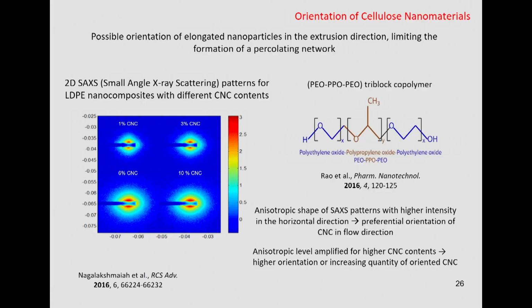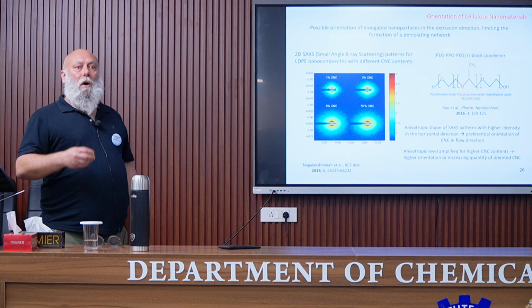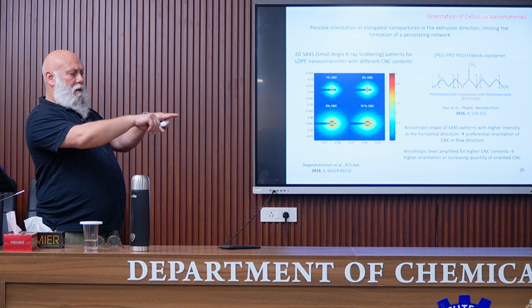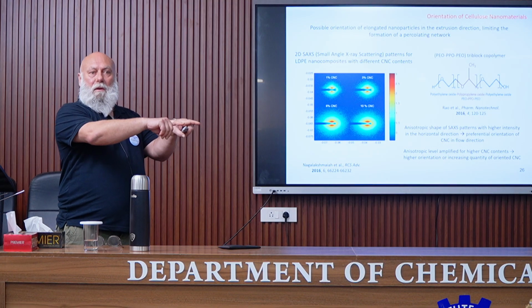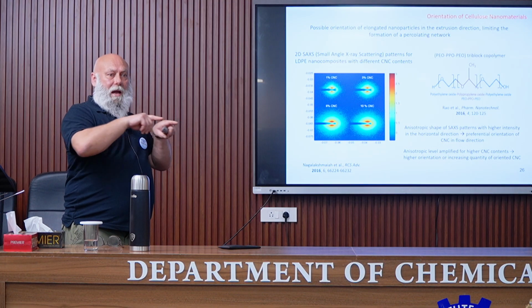Of course, this reduction in the length of the nanocrystals can be a problem for percolation. Another problem for percolation can be the orientation of cellulose nanocrystals. So strong shear rates are applied during extrusion or injection molding, meaning that we can have some orientation of the nanorods in the direction of the flow.